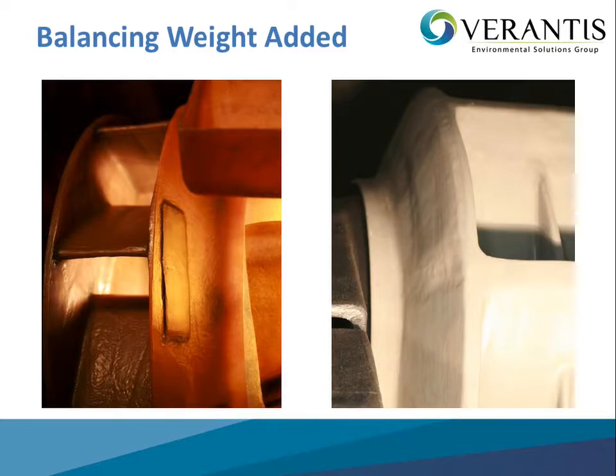Now in balancing, we always add weight to our impellers when balancing. Adding dissimilar material, as shown on our competitor's fan on the left, can be prone to delamination and can result in unevenness and problems when balancing. And if you look right here, you can see this is already starting to flake up a little bit, which is going to be subject to attack.